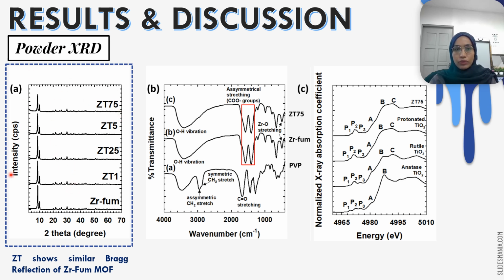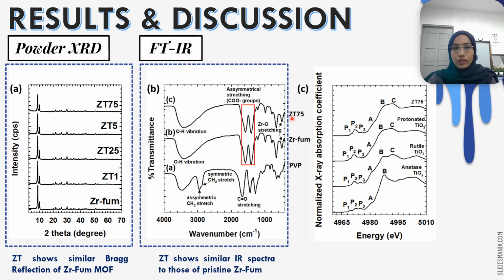As we can see from this powder XRD pattern, all of the ZT nanohybrids show similar Bragg reflections to that of the zirconium MOF. So we can say that the ZT nanohybrid has been successfully synthesized. And then I characterized all the samples with FTIR spectra.